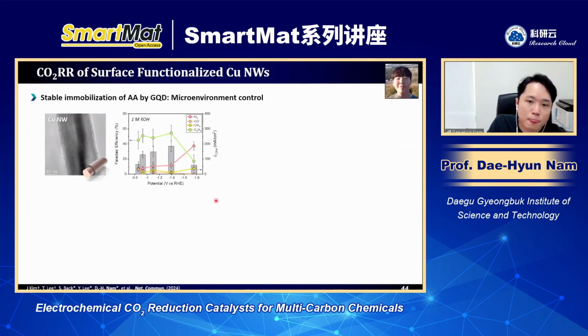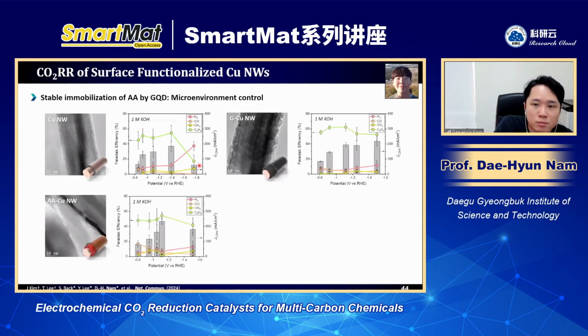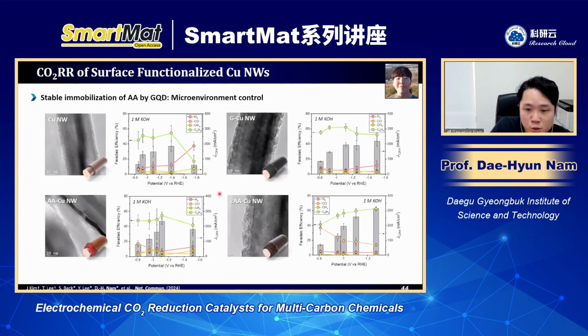So for example, in the case of bare copper nanowire, if we increase the potential, at the first time we can have a high ethylene FE. But as we can expect, if we increase the potential and the current density, then the ethylene FE degrades because of the CO2 mass transport limitation. I'm going to show this one. But in the case of the ascorbic acid with the graphene quantum dot,